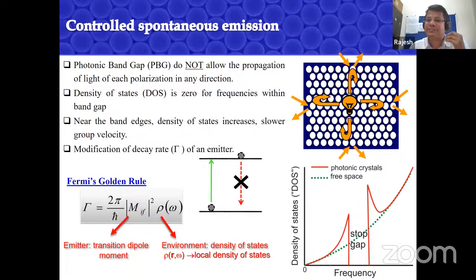And now if you have a system where the density of photon states is 0, look at Fermi's golden rule. In quantum mechanics, suppose you have a 2-level system, you excite an emitter, and the decay of that emitter, the 2-level system, depends on a term called rho, which is the density of photon states. So now I have a system where the density of states goes to 0, and that means theoretically or ideally, I have a system with a decay rate of 0, and decay rate is inversely proportional to lifetime. So I have an infinite lifetime. So I can inhibit the spontaneous emission of light sources using a photonic band gap.